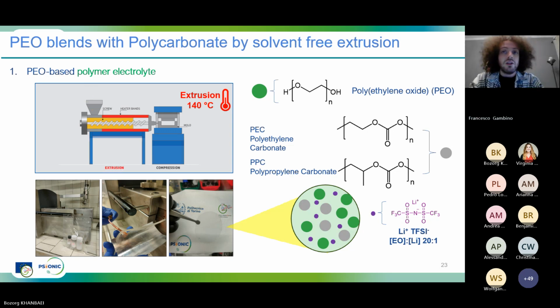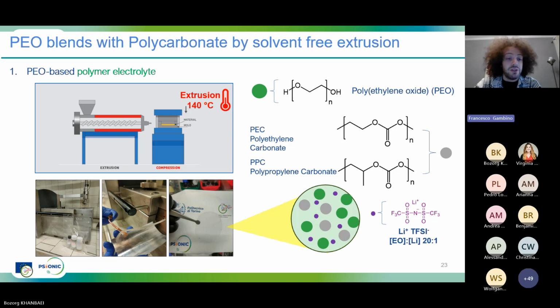Thanks. So this is where our work started. We started from the preparation of our polyelectrolyte. We employed an extruder to blend polyethylene oxide with polycarbonate at 140 degrees. The salt used was lithium TFSI in the constant ratio of 20:1.